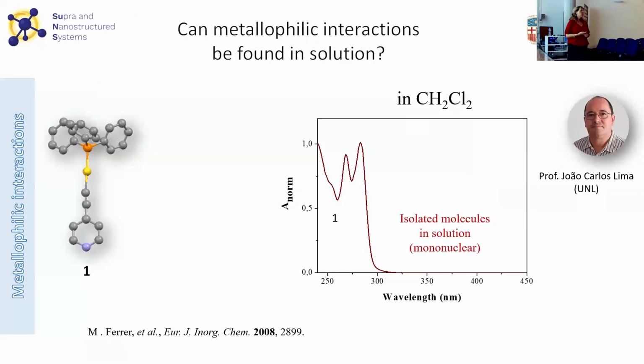Okay, so this is in solid state. What happens in solution? Well, in solution we also made a systematic study with similar compounds with this pyridyl ethinyl chromophore, and this was made in collaboration with João Carlos Lima, at the Nova University of Lisbon. In this case, we performed absorption spectra of the compounds. So this is the absorption spectrum of this compound that presents a vibronically structured band, which is due to the pyridyl ethinyl chromophore.